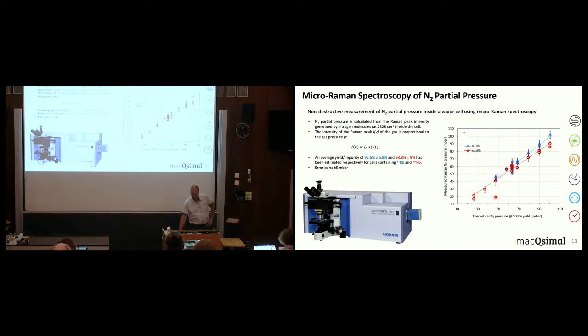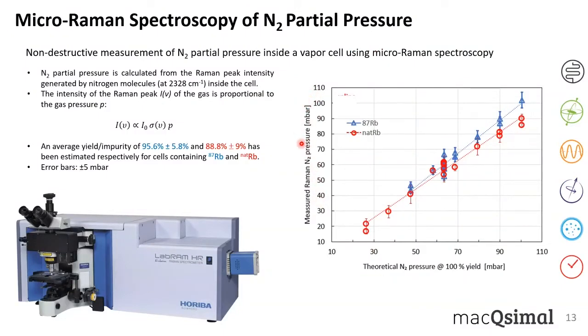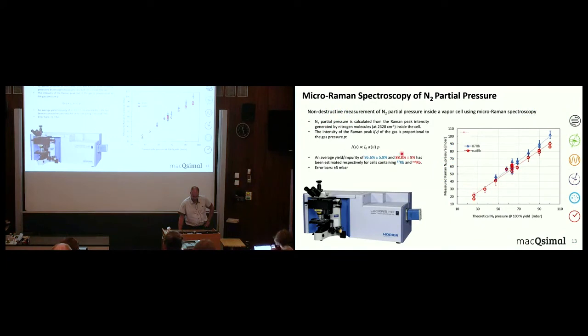If you look at the graph, we plotted the theoretical nitrogen pressure that we should have at 100% yield, and we looked at the measurement from the Raman spectrometer, and of course this should be a linear line. You see here at 100%, we are only at 88% for the case of natural rubidium azide. If you look at the error bars, they are approximately 5 millibar, which is a very good value and which is largely sufficient to estimate the gas pressure.